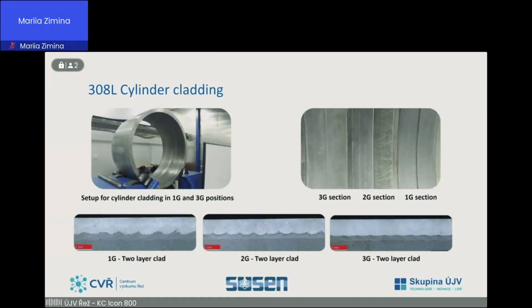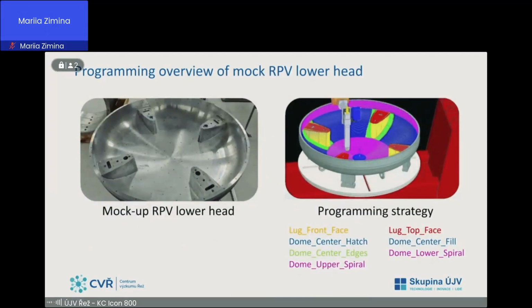The cladding procedures are being developed using three welding orientation positions as described in ASME Section 9. These are 1G flat, 2G horizontal up, and 3G vertical. In the picture you can see deposited layers of austenitic steel 308L on the base material. The application parameters of the corrosion-resistant coating vary with respect to the inclination of the surface to be treated.